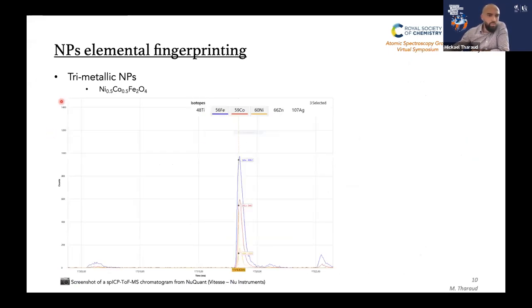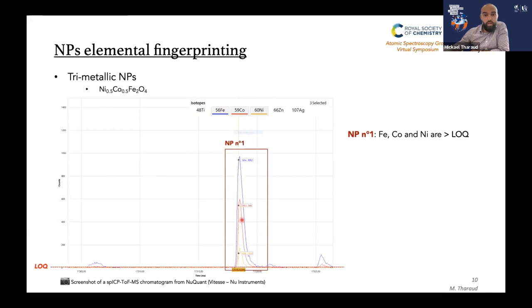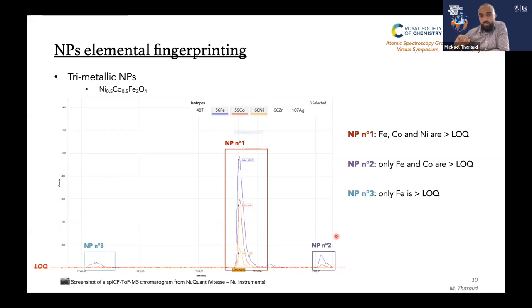So when we go back to the chromatogram displayed by NuQuant, which is the software of Vitesse, and add the limit of quantification of the three elements, which is roughly the same for the three selected elements here, we are able to distinguish the three different kinds of nanoparticles. The first one where iron, cobalt, and nickel are way above the limit of quantification. A second population where the mass of iron and cobalt is high enough to be above the limit of quantification, and a third kind of nanoparticles where only the signal of iron is above the limit of quantification. Basically, this is due to the fact that the mass of the first kind of nanoparticles is way higher than the mass of the second type, itself way higher than the mass of the third category.